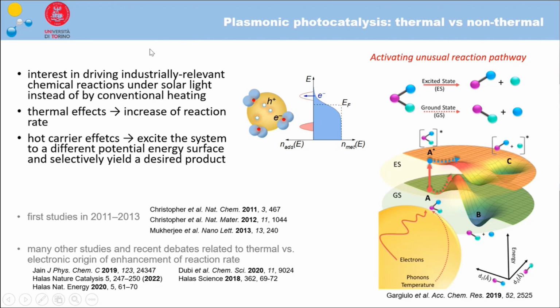In particular, as we have seen, we are able to generate highly energetic carriers, or we can also generate at the same time intense local heating. So it's important then to determine how the chemical reaction under study basically speeds up. So is it a thermal effect or a non-thermal effect due to the hot carriers that we produce.